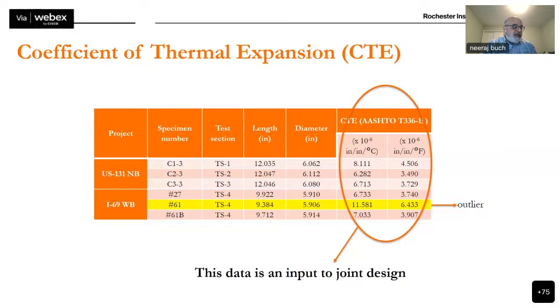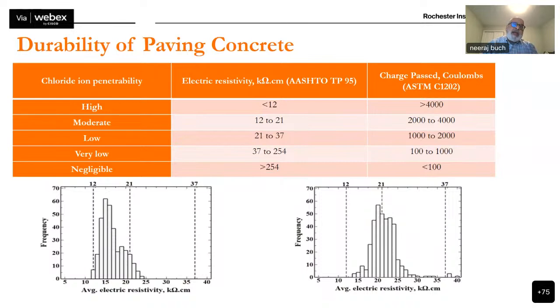The reason why coefficient of thermal expansion is so important is, and I don't have time to get into joint design, but joint design is extremely significantly dependent on coefficient of thermal expansion. The spacing of the joint, the size of the joint width, as well as the curling stresses are very important when it comes to joint design, and they are directly related to the thermal capacity and the thermal properties of the concrete pavement. So again, that is why coefficient of thermal expansion is such an important measurement when it comes to characterizing material properties. We also measured the electric resistivity of the concrete.